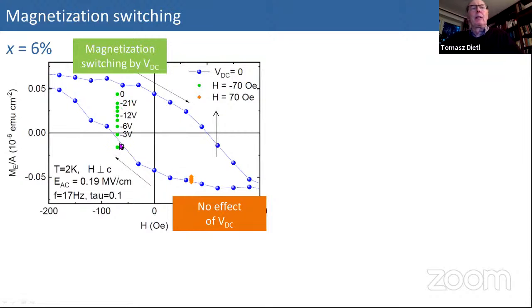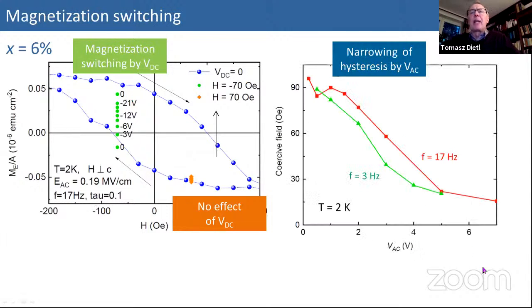So by introducing the electric field here, we kind of move towards equilibrium states. Magnetization wants to be directed along the negative magnetic field. And we can do another experiment. We can look for coercive fields in a large AC electric field. Here, I recall, we have a small AC field, and we add a DC field. Now we switch on a large one, we measure as a function of large AC field, and we see that this coercive field decreases with electric field, independently of the actual frequency which we use. So we have narrowing of hysteresis, which is caused by this AC field. So it's kind of an interesting effect.